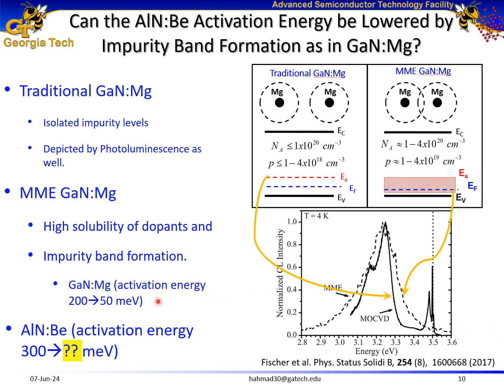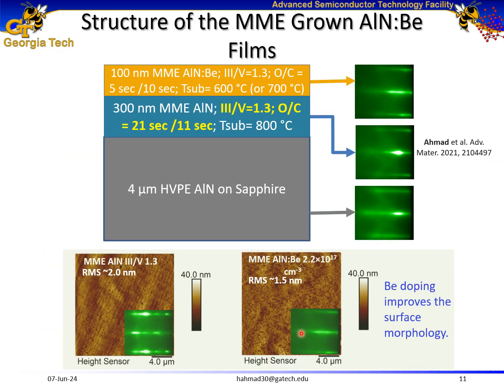So we have achieved an improvement in terms of activation energy for magnesium doped gallium nitride, reducing it from 200 to 50 milli-electron volts as compared to literature. So now we wanted to see if we can improve the activation energy of beryllium in aluminum nitride as well. This led to my study of growing beryllium doped aluminum nitride on top of HVPE aluminum nitride templates with buffer layers. We achieved streaky reflection high energy electron diffraction patterns indicating smooth surface morphology.